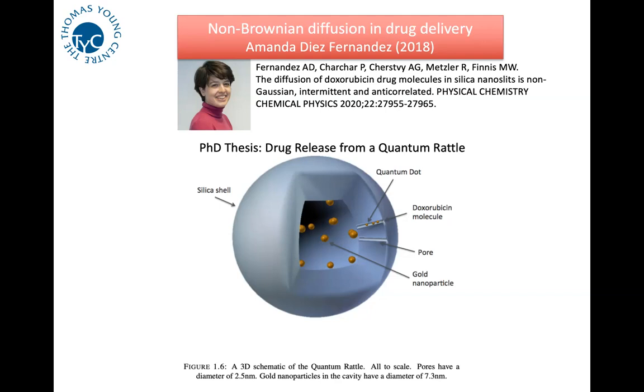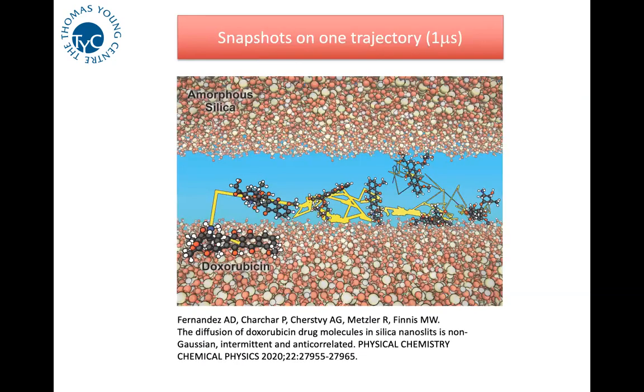And it wasn't quite as easy as that, but this was a snapshot that when we'd done the job, reached the cover page of PCCP, and there's a doxorubicin molecule that's diffusing in a random way in water trapped between two silica slabs. And this was a model of diffusion, a confined diffusion of doxorubicin. And now, interestingly, this turns out not to be standard Brownian motion. And so that's what